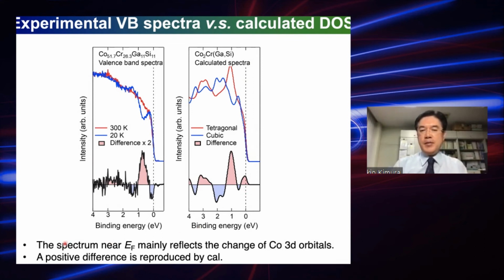Anyway, the spectrum near the Fermi energy mainly reflects the change of the cobalt 3d orbitals. The positive differences are also reproduced by the calculation, as I mentioned. The Fermi energy position is lowered in the experiment due to off-stoichiometry. Actually, the calculation was made for the stoichiometric samples, while the experiment was done for these off-stoichiometric samples.